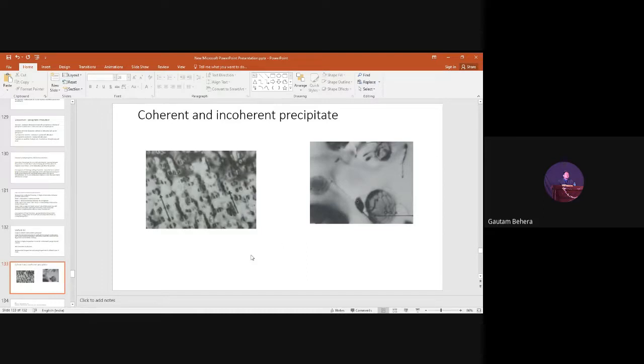If there is any strain field around the materials in a transmission electron microscope, we are able to see the strain fields. So basically these are strain fields. Due to these strain fields, we can see the particle size here. Actually this is not the particle size, the particle size is very small. And you can see this is an image showing bigger particles, incoherent particles, and you can see dislocation interaction is there. The dislocation is interacting with the bigger particles here. You are able to see the dislocations here.